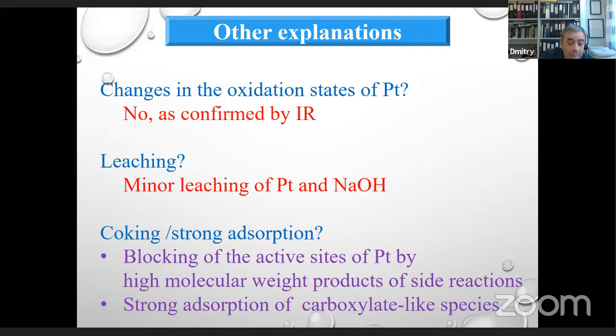Coking or strong adsorption? In fact, yes, because blocking of the active sites of platinum by high molecular weight products of side reactions is a possibility. And also we have confirmed that there is a possibility of strong adsorption of carboxylate-like species on the surface.